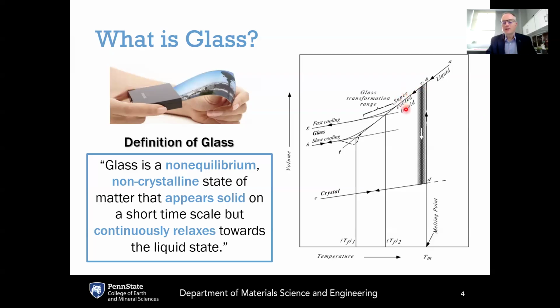The supercooled liquid is not a thermodynamic equilibrium phase. The equilibrium would be the crystal down here. Instead, the supercooled liquid is what we call a metastable equilibrium, meaning that if you leave it unperturbed, it will stay in its supercooled liquid phase for an indeterminate amount of time. However, if you perturb the supercooled liquid and give it enough thermal energy so that it can crystallize, at that point, it will undergo a first order thermodynamic phase transition. The supercooled liquid will crystallize into the solid state and achieve its true thermodynamic equilibrium.